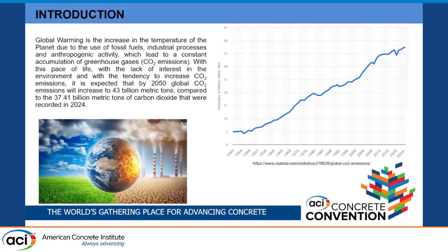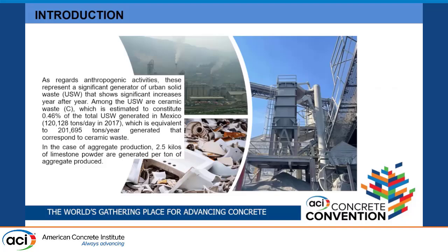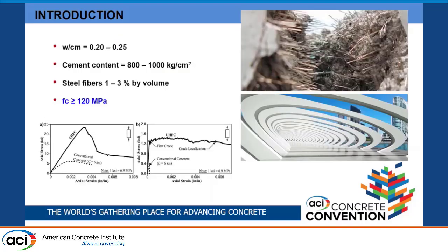So that's why we are considering this byproduct to substitute the cement, mainly the cement in this type of concrete. Why the cement? Because this type of concrete demands around 800 or 1,000 kilograms of cement per cubic meter. So that's a major benefit if we can diminish the amount of cement. These types of concretes were developed between the 1980s and the 1990s because of the appearance of the high-range water-reducing admixtures that allow us to produce concrete with very low water binder ratio.